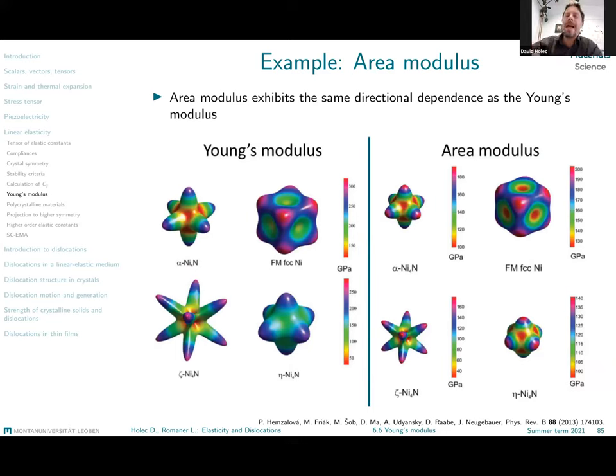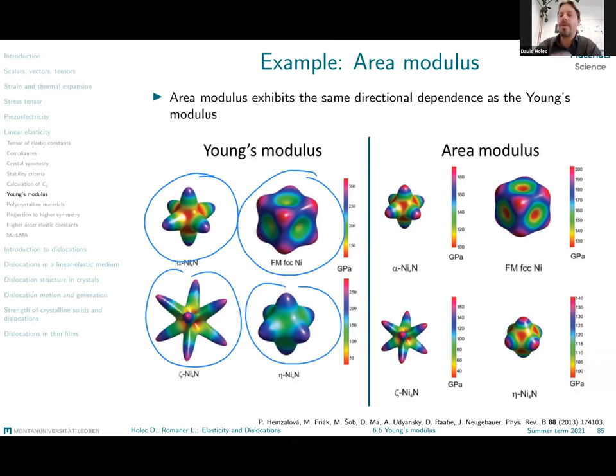This fact, that the 3D representation or the directional dependence of those two quantities is identical, is represented in this example of a lot of different topologies of Young's moduli, all of those for different nitrides, from, let's say, a more standard distribution. We know already those two types of blobs, to a more extreme type of distribution where we have extreme differences between some directions, the 111 as the softest and the 100 as the stiffest, to very, very extreme distributions which are at the border of stability.